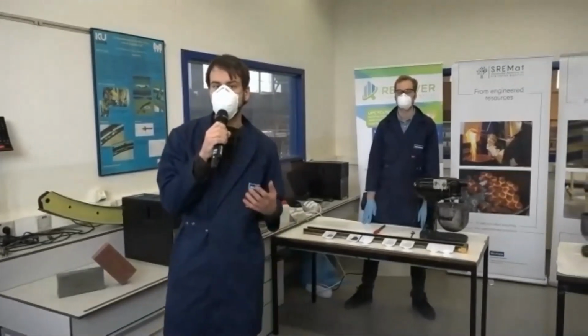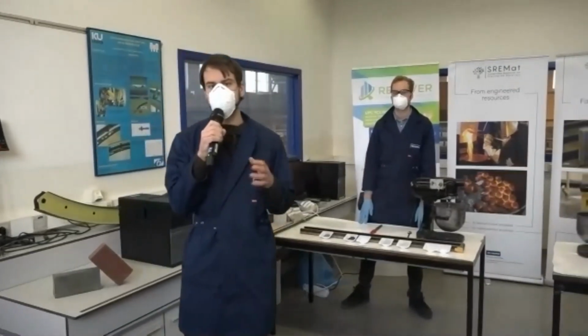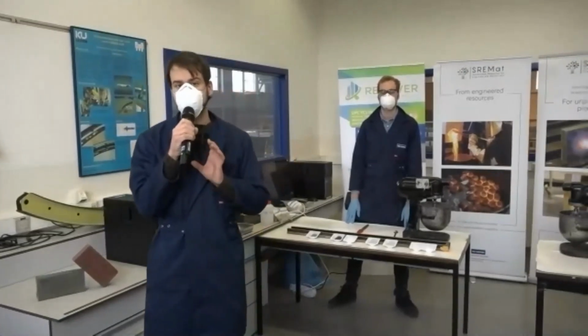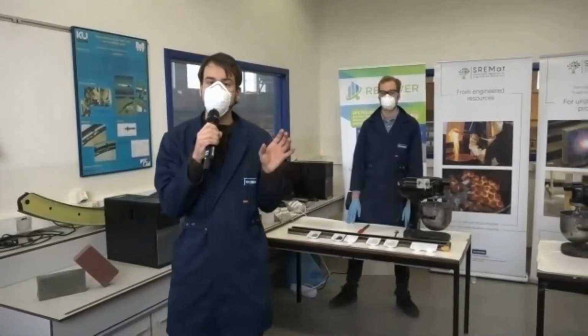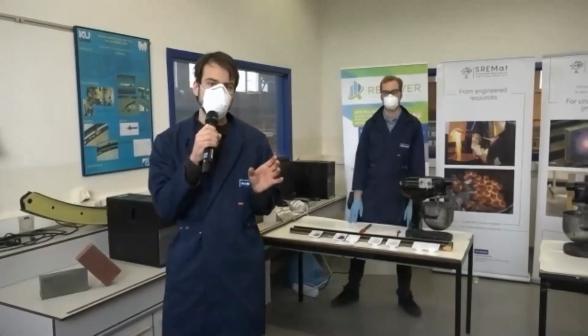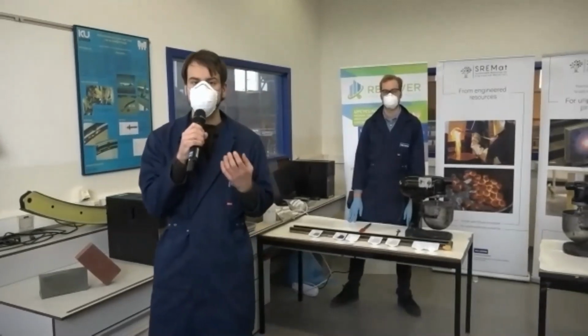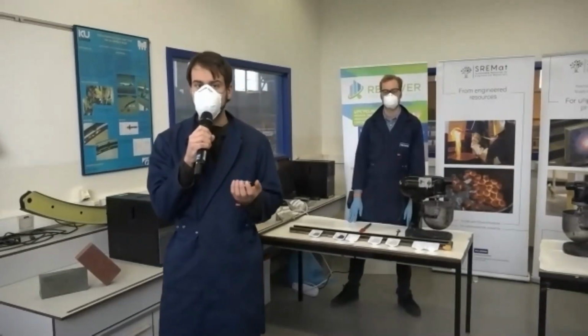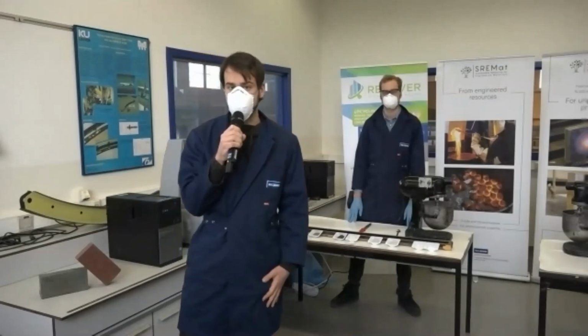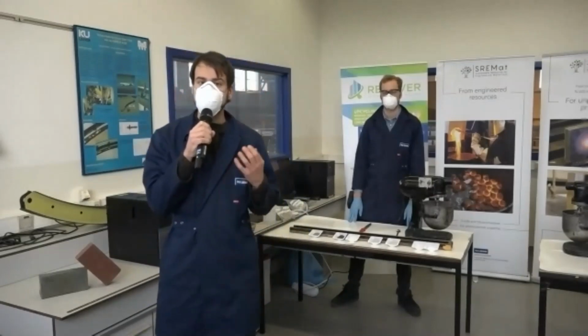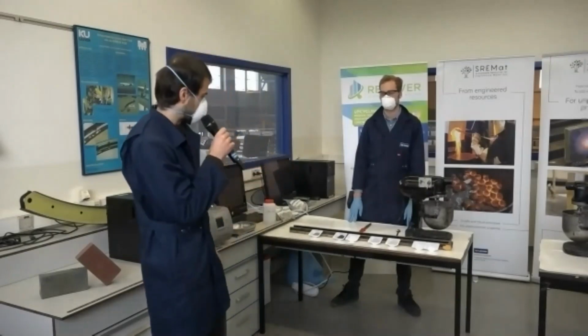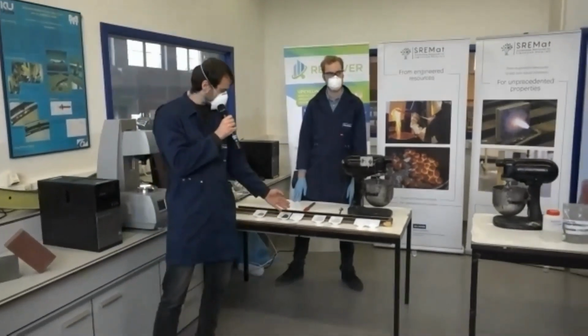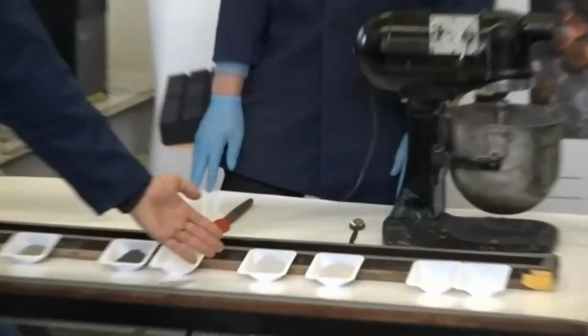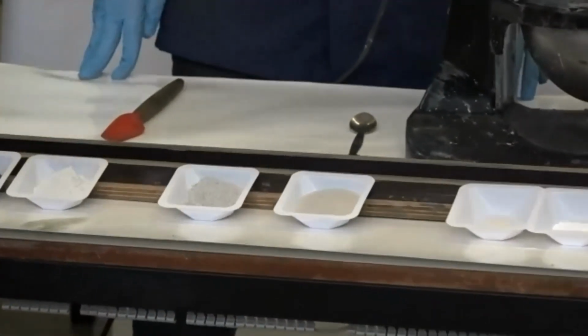The hybrid binder is kind of a compromise technology between a normal cement and an inorganic polymer. The reason is that we add a slight amount of cement together with the main precursor, which will be a slag, for instance, like Corus, Boliden, or theoretically also vitrified red mud. And we have some filler materials. You can see that here on that bench, for instance.